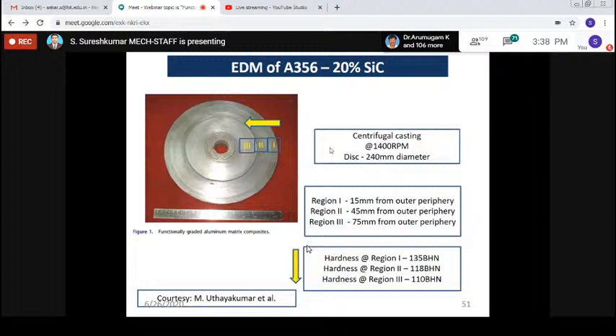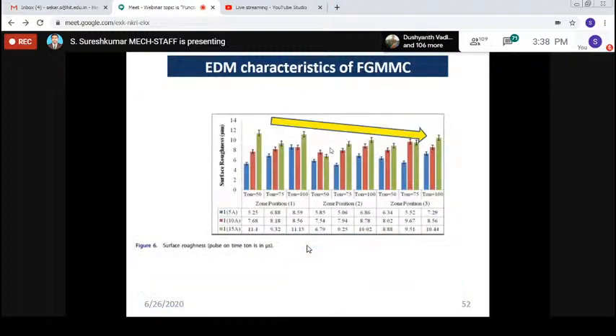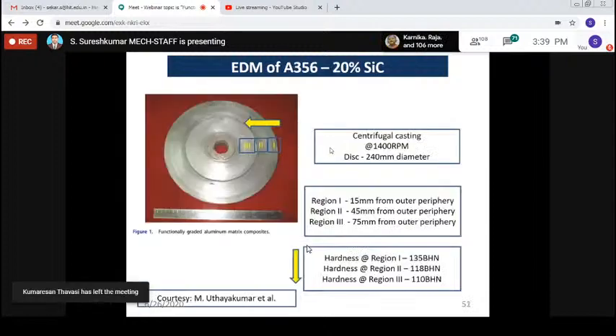And what are their machinability responses? Maybe in terms of surface roughness there are no significant variations, but of course in zone 3 and maybe the middle region there is some variation. Of course, no defined trend is noticed, but some variation in surface roughness is noticed. I told you in zone 3, where the least reinforcement section is available, the machining process is easy. That's the reason why lower surface roughness is obtained. I mean, a good finish is obtained in the inner section, zone 3, the inner section of the rotor disc.